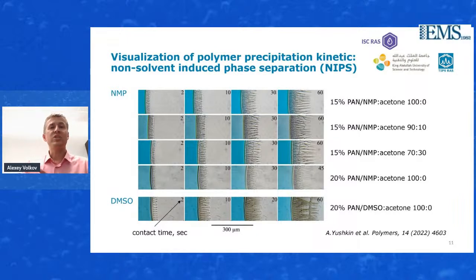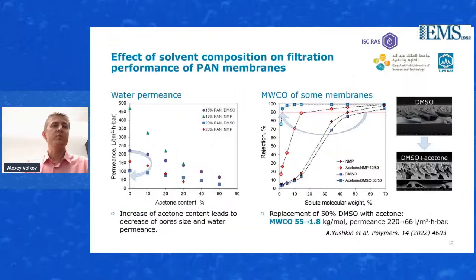It means that by changing the composition, we are able to play around and yield different structures of the porous membranes. And that is just a confirmation that we replaced 50% of the DMSO by acetone. In that case, it was possible to change the molecular weight cutoff, if we have a look at the right graph, from 55 down to 1.8 kilogram per mole. And that is actually the first time a quite tight OSN membrane was achieved